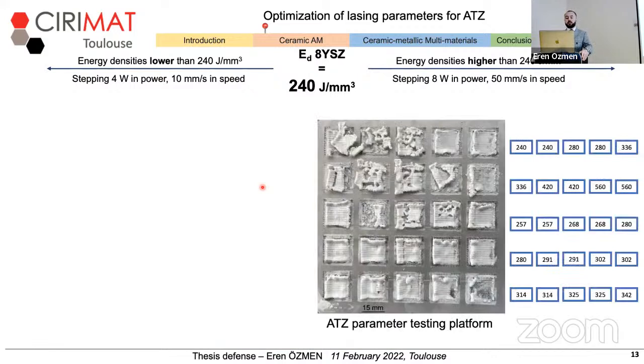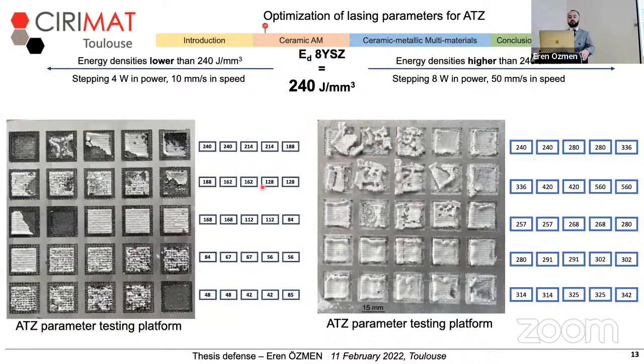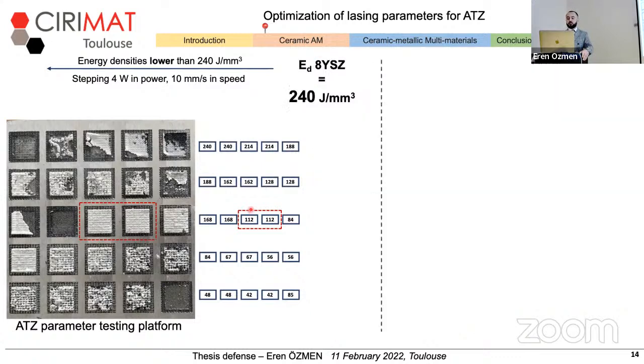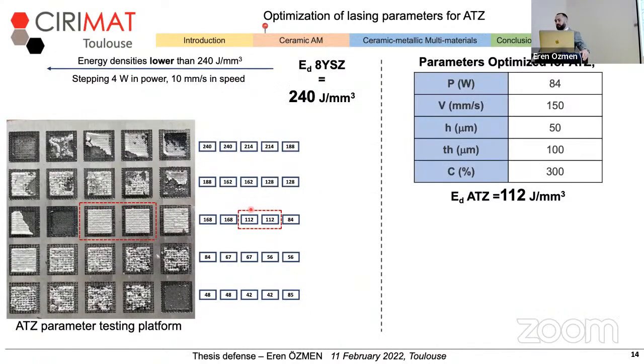So when we check the energy density higher than 240, and we check the 240 firstly, we see that pieces exist on the platform. However, with all the other pieces in the same platform, they don't match the design data, and they're full of defects. When we check the energy density window below 240, a combination of lasing speed and lasing power was giving pieces that satisfy 3 of the criteria. So I accepted this energy density value and this combination as suitable for ATZ fabrication.